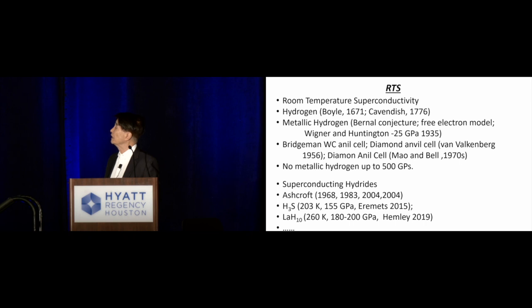And then he modified it, in 1983 and 2004, saying it should be superconducting by using chemical pressure. And that's exactly what we did in the cuprate situation. But again, there was no metallic hydrogen or compound he proposed that became superconducting. So finally, in 2015, Eremets from the Max Planck Institute in Germany announced he got superconductivity in the H3S hydrogen-sulfur compound, with a transition temperature of 203 degrees Kelvin under a pressure of 155 GPa, and he announced that.